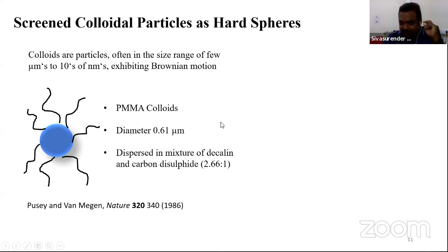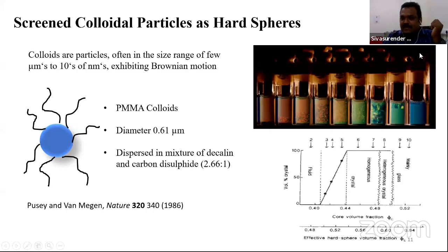And now once they could create it, going back to our discussion, can this crystallize experimentally? And here what I show you is a series of vials. These are the colloids dispersed in this solvent, the colloidal solution. Going from left to right is the direction in which the volume fraction of the colloids is increasing, right? So at the lowermost, you're starting with something like 20% volume fraction, to the highermost, where you are going up to like 70% volume fraction of the colloids. And if you look at the leftmost vial, you see a rather homogeneous color, right?